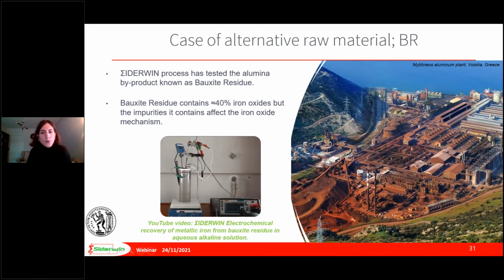Okay, the Siderwin project, except for dealing with the pure iron oxide reduction, has also explored some alternative raw materials to investigate if there is a byproduct that can be used as a feed. Bauxite residue is a byproduct rich in iron oxide, containing around 40% of it. This material results from alumina production during the Bayer process, and its valorization is very important towards the environmental crisis. In NTUA, we have extensively tested bauxite residue as a possible raw material for the Siderwin process, and you can see more details about the experimental procedure in our video on the Siderwin YouTube channel.